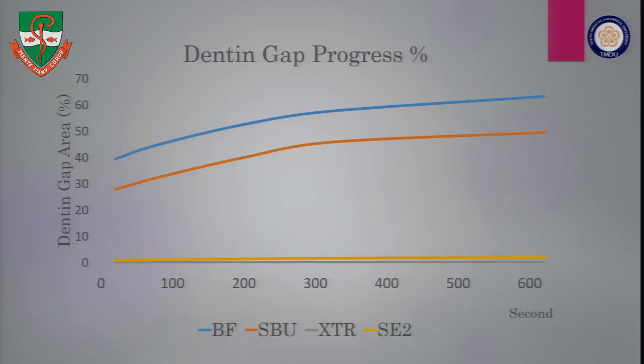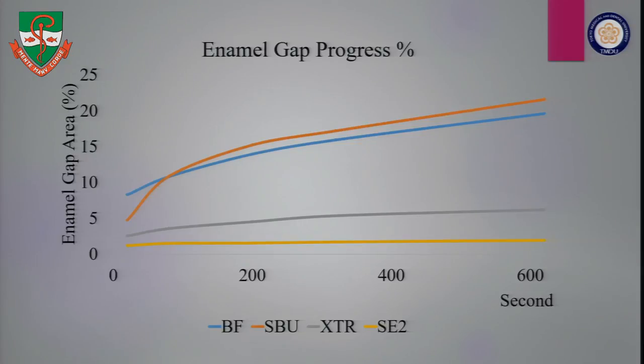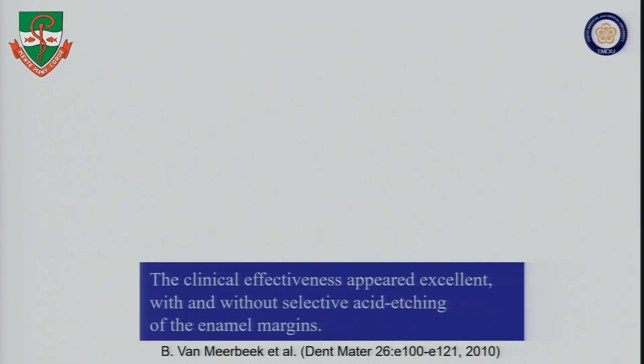Of course, the one-step system, including universal bond, showed a higher percentage of the gap progress, and the two-step system showed very good results in the case of dentin gap. And for the enamel gap, again, the one-step system showed the higher percentage of the gap progress. So from this kind of results, we have to think about the necessity of the selective etching of enamel in the case of self-etching materials.